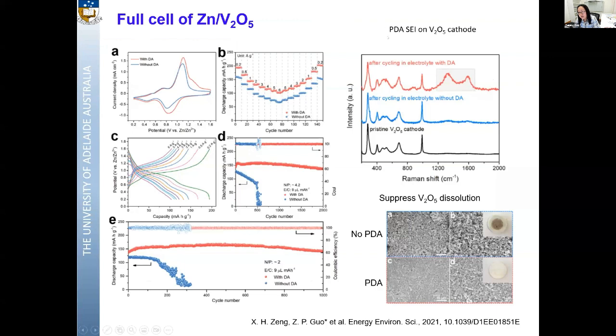And we found this PDA, this organic SEI, also formed on the surface of the cathode. When we assemble into the full cell using vanadium pentoxide as cathode, this SEI covers the surface of vanadium pentoxide and can suppress the cathode dissolution. We can see from the separator, without this PDA layer, after cycling, we can clearly see the color changed due to the dissolution of vanadium pentoxide. But with this organic SEI, the surface is quite clean. So demonstrating the suppression of the dissolution of the vanadium pentoxide.